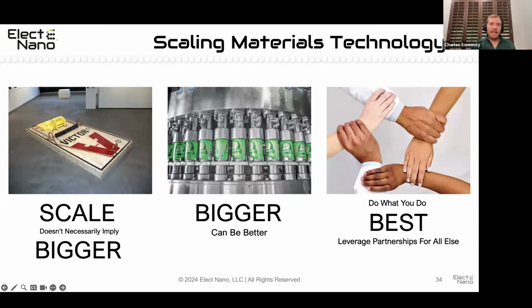A concrete example of that is in the golden days in Dr. Green's lab, we used to take 3D printer filament, and we were trying to put a thin coating on the outside of the filament with carbon nanotubes. So we'd make an ink and dip the filament into it and get a coating on there, but it was an ink that had chloroform or dichloromethane to dissolve a thermoplastic and get it on there. And we'd make a meter or so at a time. Then when we needed to scale it up, the first thing we did was make a continuous coating bath, and I ran it up the side of the Jack E. Brown Chemical Engineering Building at Texas A&M. We had this thing going up like 6 stories over a pulley and back down, because that was the only way we could get the ink to dry out before it touched the pulley and got all wiped off and messed up. And even then, that was really challenging.